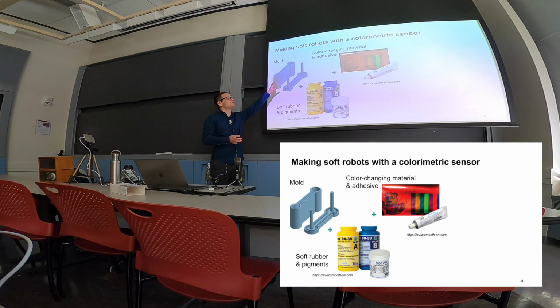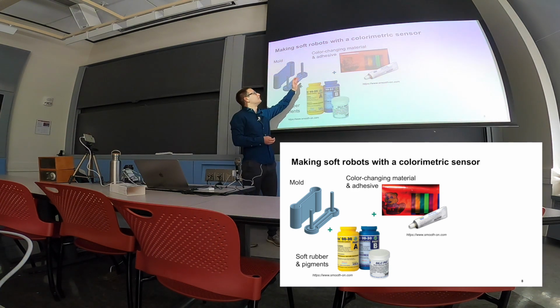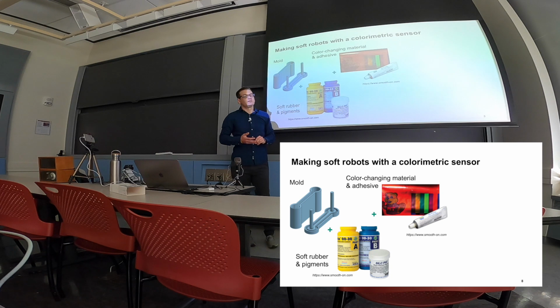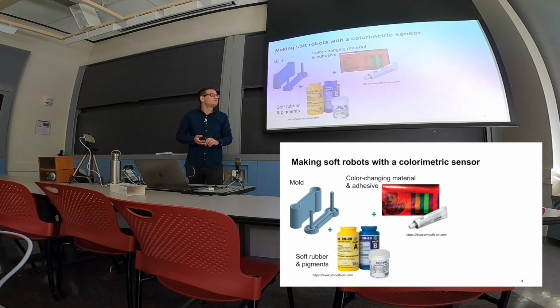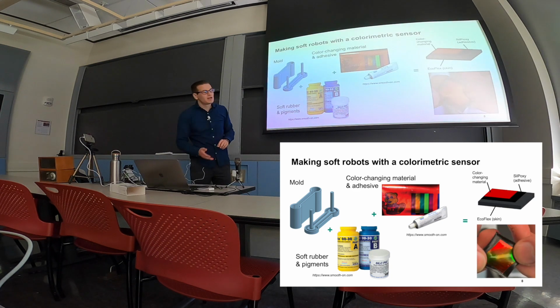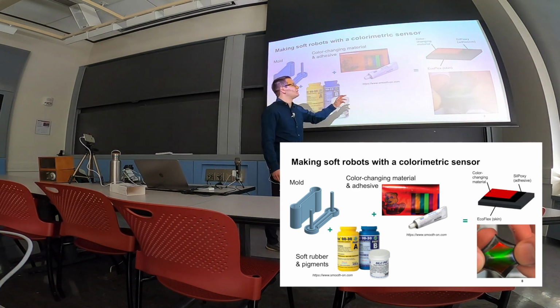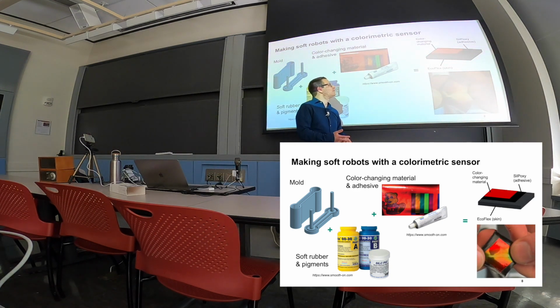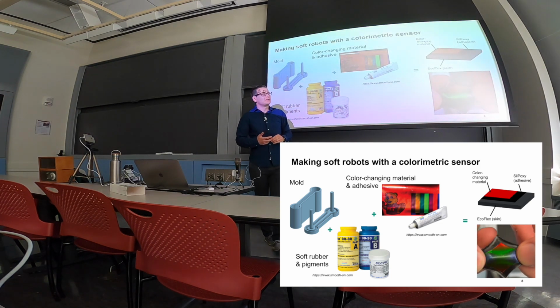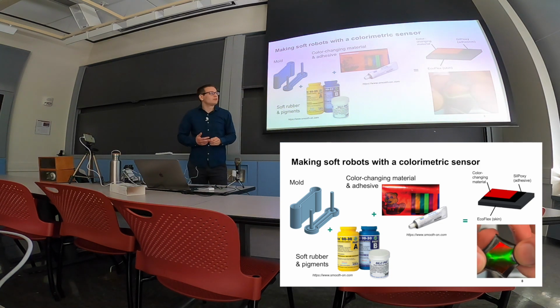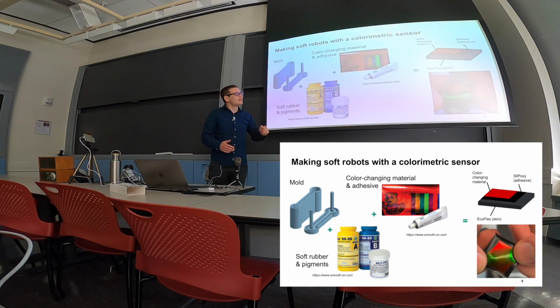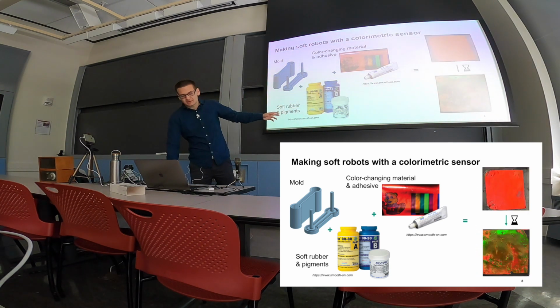For example, with this mold, we just create a skin of a soft robot. And then with some adhesive and the color-changing material, I was able to quickly and easily apply the color-changing material to such a soft robotic system. We can see the sheet that I produced ended up as what we can see here on the right side. So three layers, and it worked quite well for only playing around with it for one or two weeks. There was a good result, but there was still one problem that occurred.